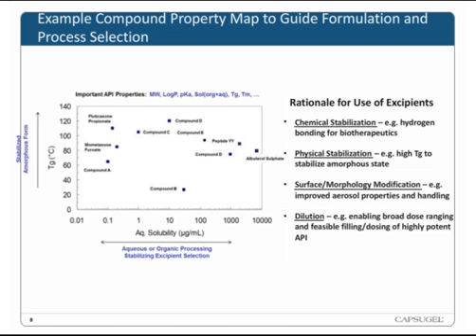So in the case where we've looked at the compound properties and we understand, okay, well, either from a formulation stability perspective or from feedback from our team collaboration at Lovelace, we say, well, this is fine to be in the amorphous form, or no, actually, either for stability or performance perspective, we need to have it in the crystalline form. Then we take that, we think about how to put that into a particle that's respirable, and oftentimes that leads to the need for excipients. And our rationale for the use of excipients centers around either chemical stabilization. So in the case of biotherapeutics, oftentimes you want the molecule to feel hydrated, with good hydrogen bonding, and so we'll select excipients that interact with it there.